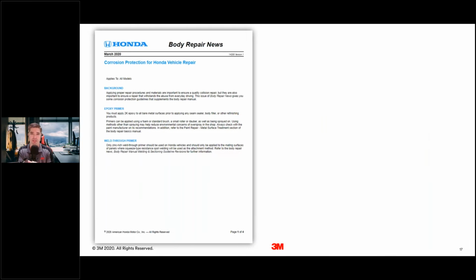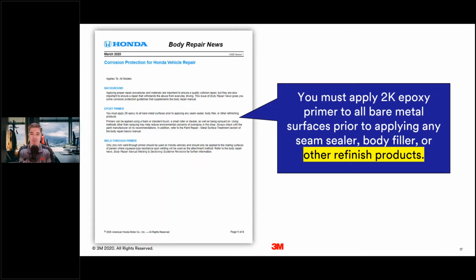If you're not familiar with it and you haven't seen it yet, Honda did just release a new bulletin. This is for all Honda vehicles. And what they're saying is you must apply a 2K epoxy primer to all bare metal surfaces prior to applying seam sealers, body fillers, or other refinish products. And I highlight other refinish products here because this also includes undercoating, chip guard coating, products like that. We need to make sure that we're following their best practices. And they go on in this bulletin right underneath this to say acceptable methods for applying a 2K epoxy primer.